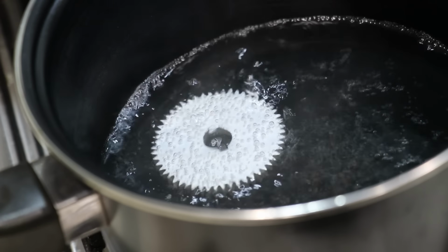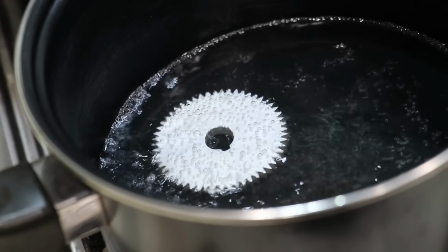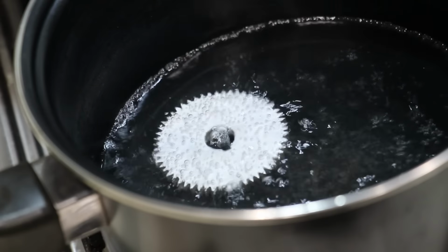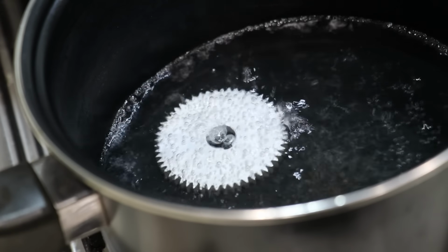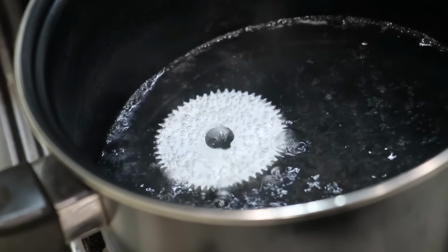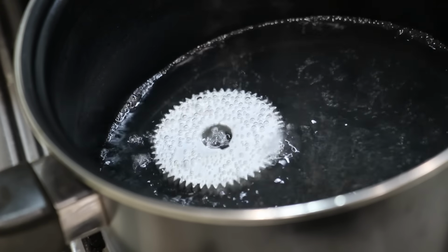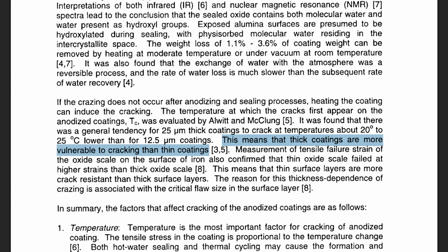The downside to this obviously is that we're heating up the whole part, and because the core, which is just regular aluminium, will expand at about 5 times the rate of the anodized coating, the anodized coating can very easily crack. With that said though, generally with these thinner coatings, say less than 30 microns, we should be able to get away with it without causing any major cracking.